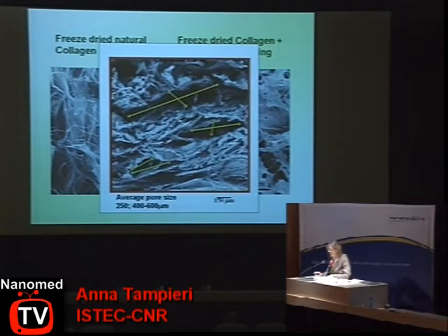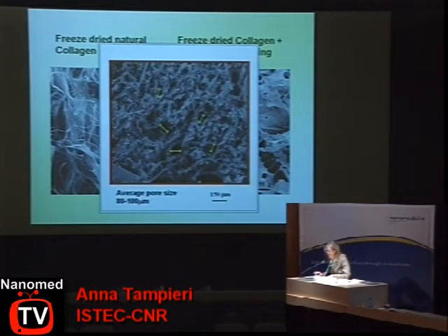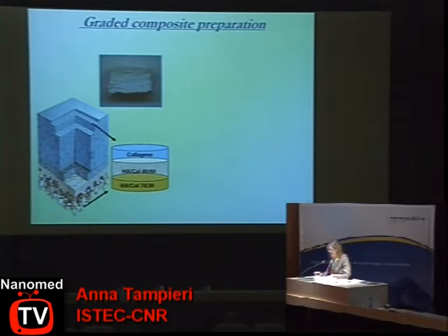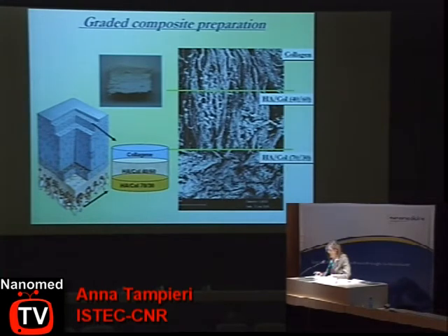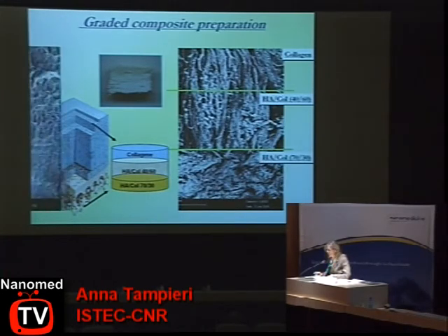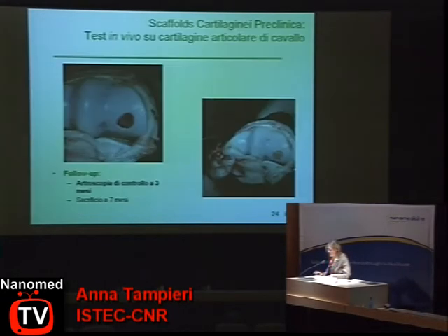So at the end, the scaffold is characterized by high porosity and high interconnection. We can also control the porosity of the cartilaginous layer, which is tailored to be smaller and with lower interconnectivity to assure a hypoxic environment, reducing the income of oxygen, as is required for differentiation in a chondrocyte-like phenotype. At the end, our graded composite was prepared. This is the final morphology, which is a macrostructure very similar to that of the natural osteochondral region.